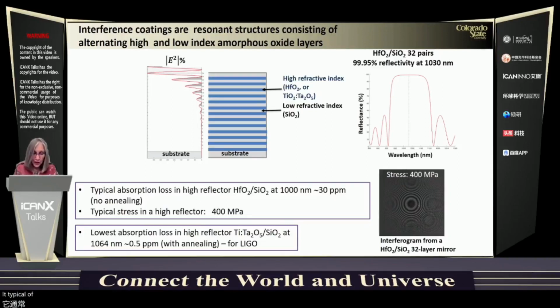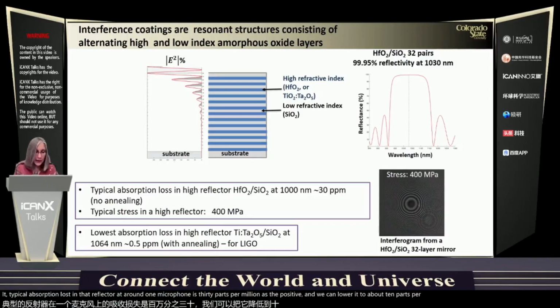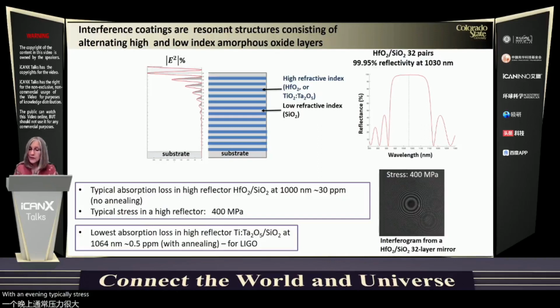A typical absorption loss in a reflector at around 1 micron is 30 parts per million as deposited, and we can lower it to about 10 parts per million with annealing. Typical stress is 400 megapascals. The stress is also reduced when we anneal. You can see an interferogram that shows the stress in this particular coating here. So it is possible to grow multi-layer dielectric coatings with absorption loss of less than a part per million. And these outstanding results have been obtained in the multi-layer structures that are used in the present LIGO coatings.